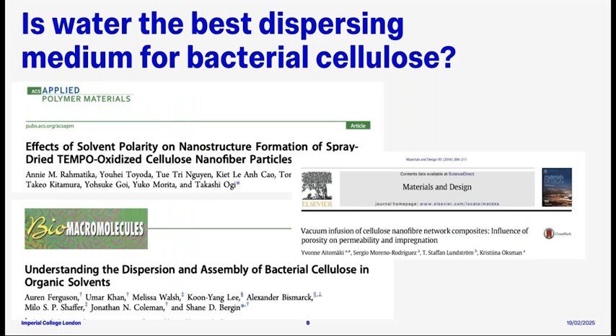And as we're looking through literature, we realize that there is a small but growing number of isolated publications that highlight the amphiphilicity of cellulose and that nanocellulose could also be well dispersed in selected organic solvents. We therefore are interested if other organic solvents would be a more suitable dispersing media for bacterial cellulose, and would this better dispersion of bacterial cellulose hence improve the quality of the coating layer and result in an improved filtration efficiency.